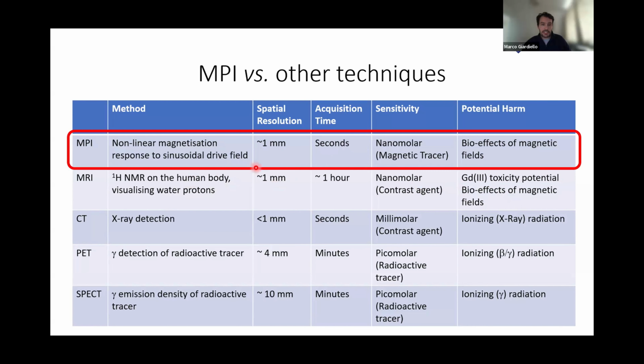You can see that MPI and MRI are similar in the sense that they create a magnetic field, but they're quite different in their applications. One comment to quickly say is that MPI, because there's no magnetic material in the body, you don't actually get any anatomical information. You only see the SPION. So in principle, you would just see a floating SPION in the middle of black space. So it will always need to be accompanied by another imaging technique, and very often that's CT.